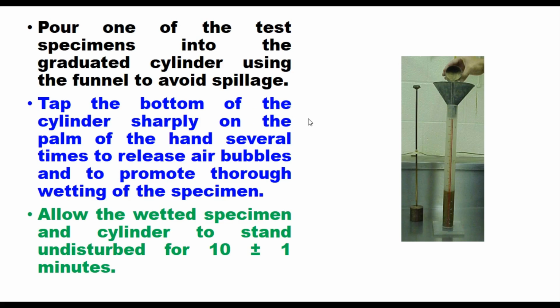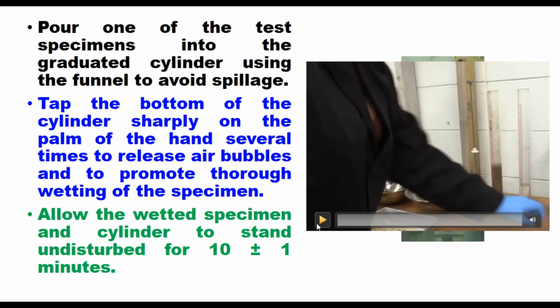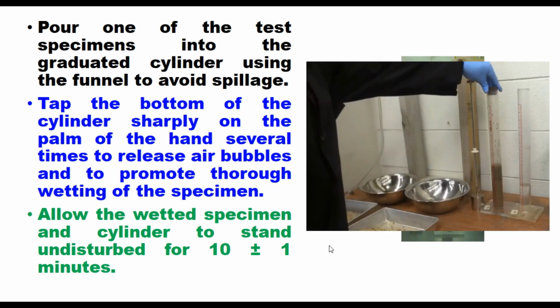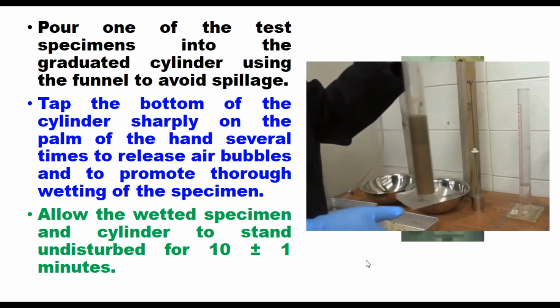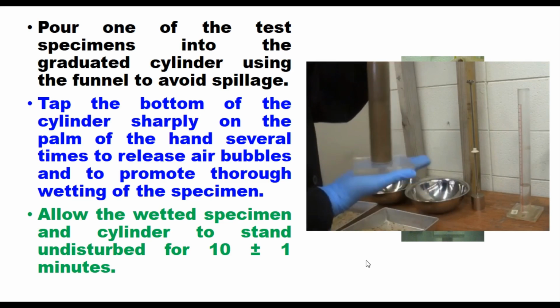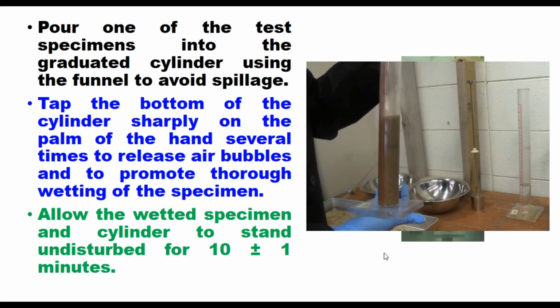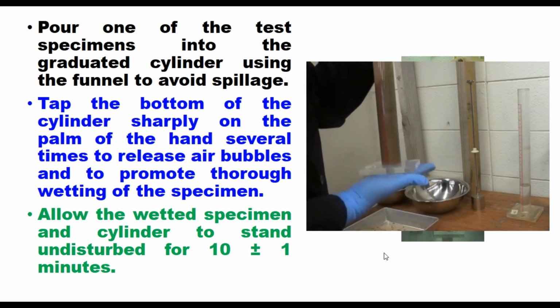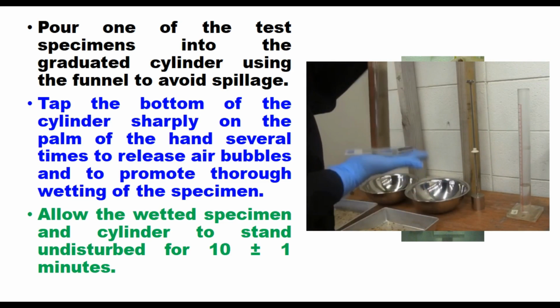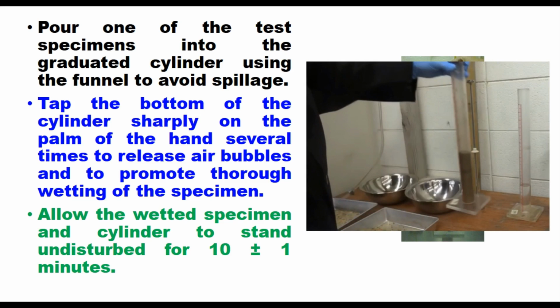Pour one of the test specimens into the graduated cylinder using the funnel to avoid spillage. At the same time, tap the bottom of the cylinder sharply on the palm of the hand several times to release air bubbles and to promote thorough wetting of the specimen. Allow the wetted specimen and cylinder to stand undisturbed for 10 minutes.